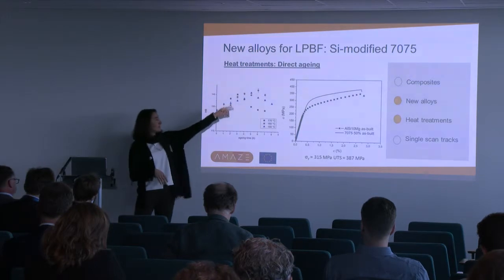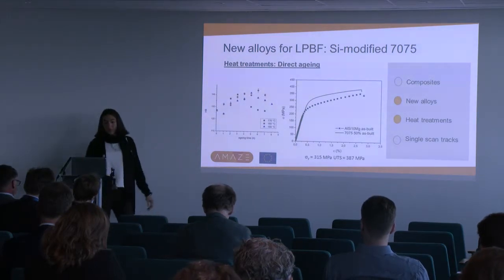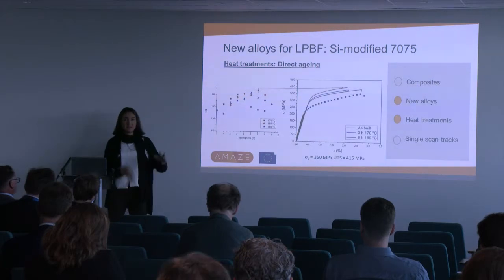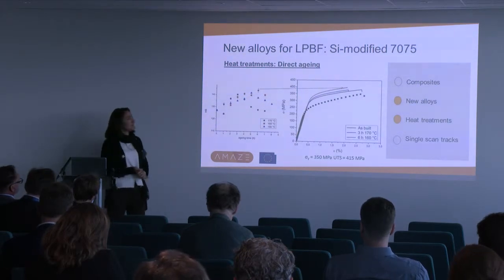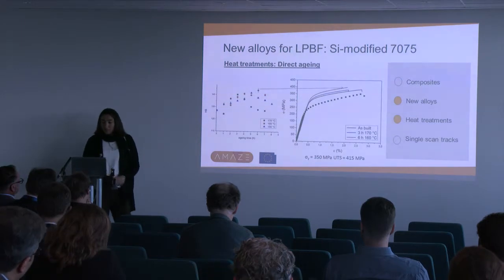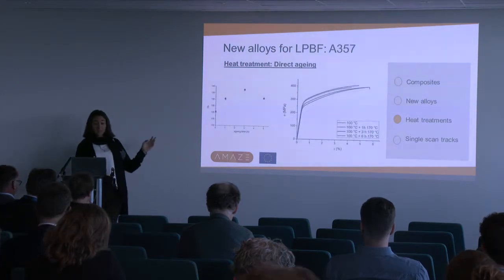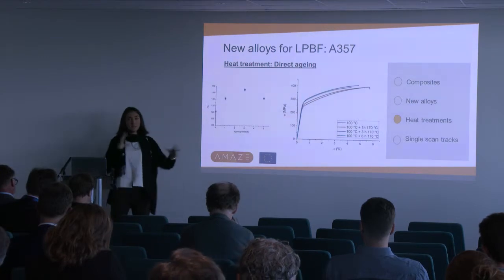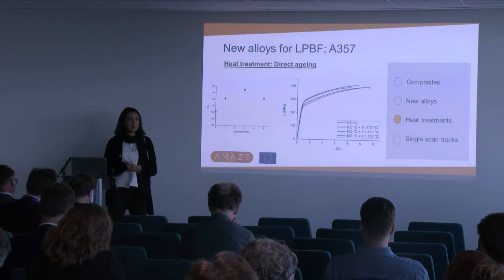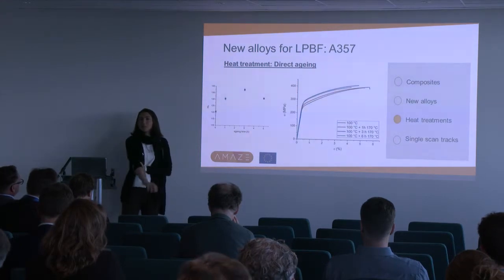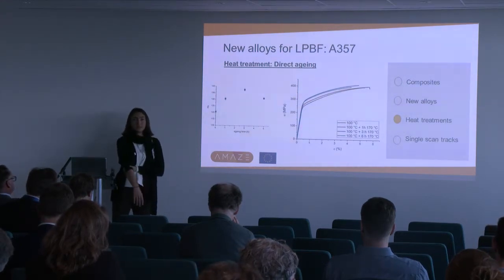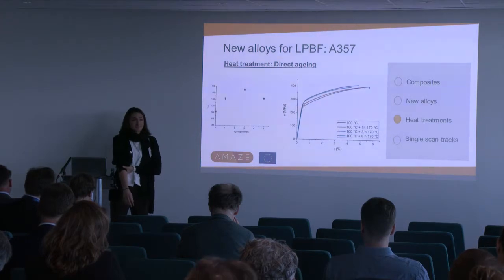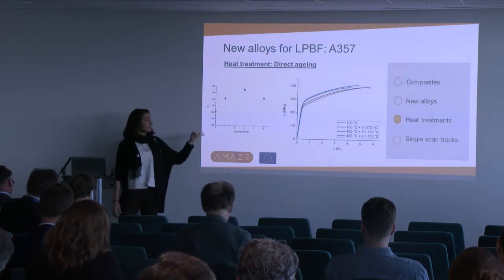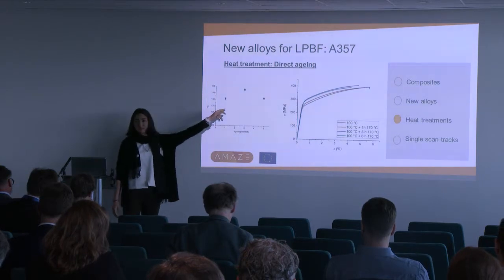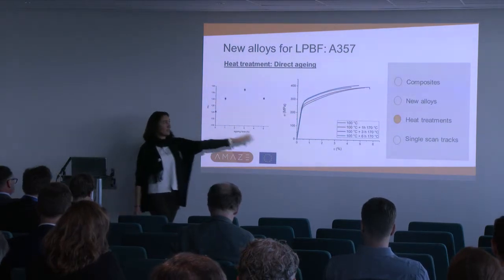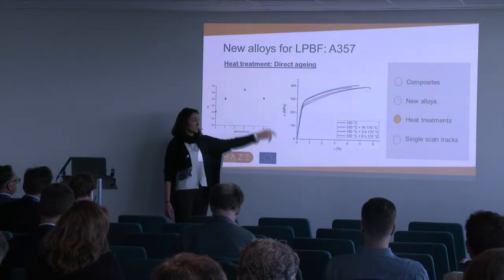So we could see that the hardness increases. And we selected two of these heat treatments, and we could achieve a 10% increase in the tensile properties. So as this heat treatment was promising, we applied the same idea to an A357 alloy. So this is an alloy very similar to the aluminum silicon 10. It contains 7% of silicon. And so we did the same thing. We built the alloy. We checked the hardness. It increases with the time. And so we did this heat treatment on tensile samples, and we could also achieve an increase of mechanical properties.